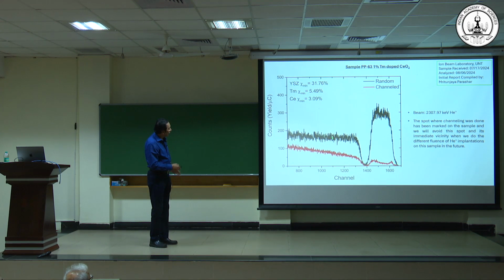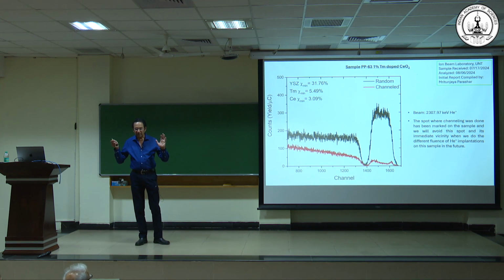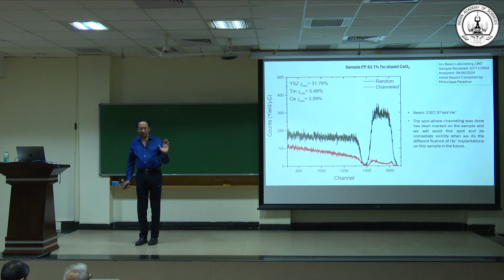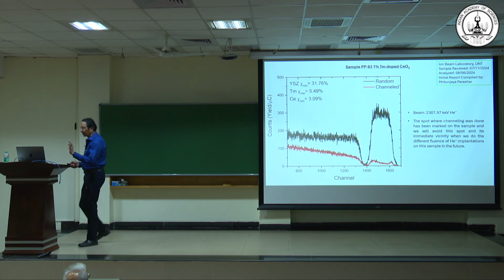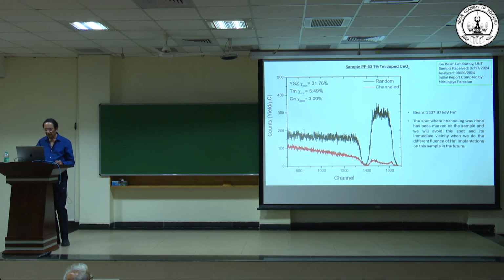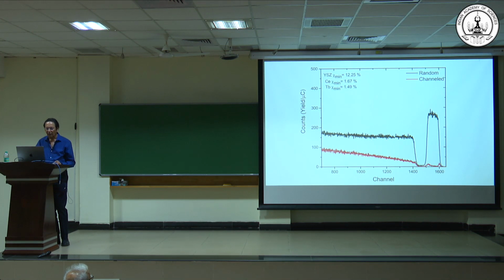It shows that we have actually put thulium atoms in the place of cerium atoms, and essentially we can do that to an accuracy of better than 95%. 95% of the thulium atoms go sit in the cerium site, which is very beautiful, okay? And these are beautiful crystalline films we are able to make now, and so this is exciting. Same thing for terbium. We can do terbium atoms too.